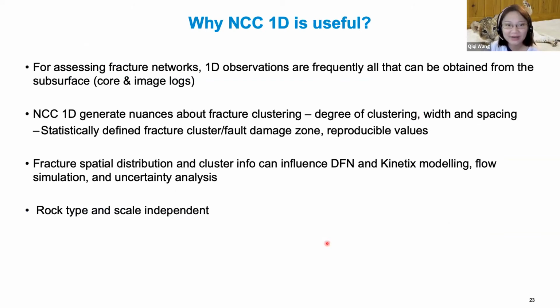Okay, so with the 2 examples, we can now have a discussion. I think this method called NCC or normalized correlation count method is useful. The abundance of fractures and their spatial arrangement are very challenging to measure in the subsurface. For assessing fracture networks, 1D observations are frequently all that we can obtain from the subsurface, from core or from image logs. And this NCC 1D can generate nuance about fracture clustering, including degree of clustering, the width, and the spacing. And we can get statistically defined fracture cluster width, like if we're studying fault damage zone width, right? And the numbers generated are reproducible values of those width and spacing. So such info can influence your DFN model or your Kinetix modelling.